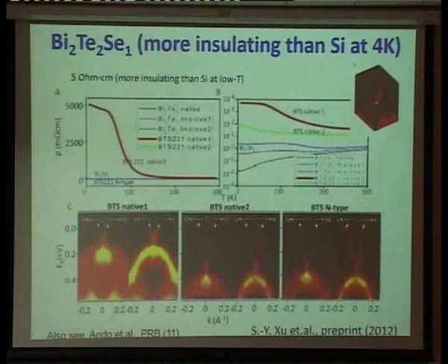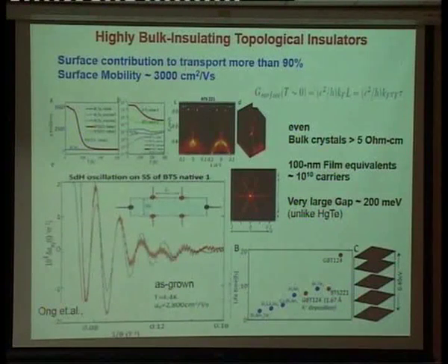And the different line? Oh, the different line is a different material. Sorry. This is bismuth telluride, and this is a modified material, bismuth tellurium selenide. It's prepared in two different states. These are your standard bulk samples, without applying a gate. The native BTS samples have the Fermi level in the gap, but the catch is that the present mobility is low. Mobility is like 3,000, so the mobility has to improve.